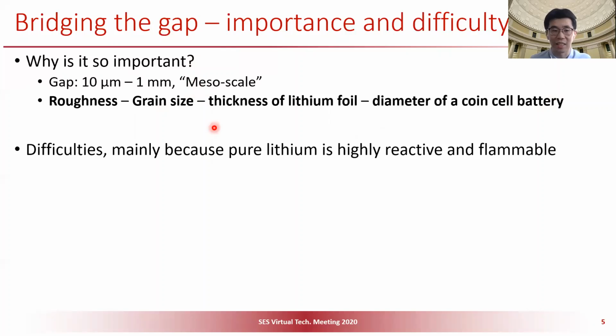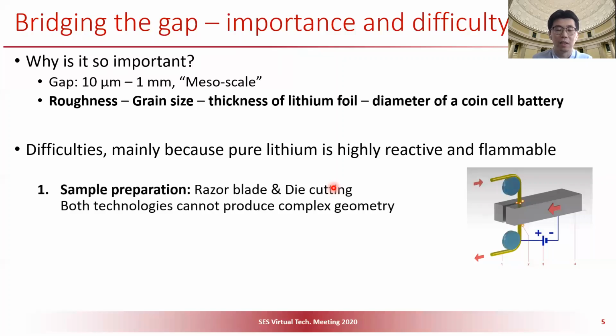oftentimes investigated. Because there are 3 difficulties, mainly because pure lithium is highly reactive and flammable. The first difficulty is the sample preparation. So currently, many people just use razor blade or die cutting, but these 2 technologies cannot produce very complex geometry. And of course, we can use some advanced technologies like EDM, but cooling is a very difficult problem, and cleaning is very difficult. And the testing has to be performed in a gas-protected environment. For example, a glove box with argon. This is a very common choice.